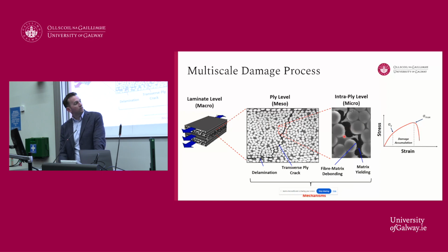Together, all of these damage mechanisms accumulate during this phase of the stress-strain curve, and they ultimately lead to failure by reaching a saturation or limit, which leads to an overall crack within the material. That's how any material will ultimately fail. My PhD was about developing micromechanical models to predict that process, to better understand why material failure happened in composite materials.